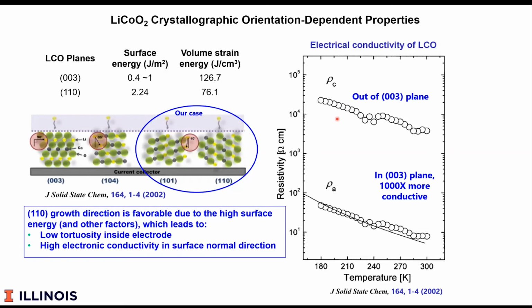We only have a vague hypothesis at this point about why we can grow certain growth directions. Superficially, one can look at surface and volumetric strain energy, but this ignores any of the effects of the solvent the electrodeposition is done in. If you superficially look at the surface energy of the systems, it is favorable to expose the 003, and you'll see these grow in deep crack-like morphologies. So having this orientation probably reduces surface energy, but I don't want to take that too far because the science is just not there at this point.